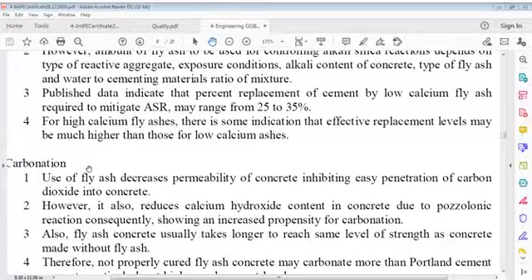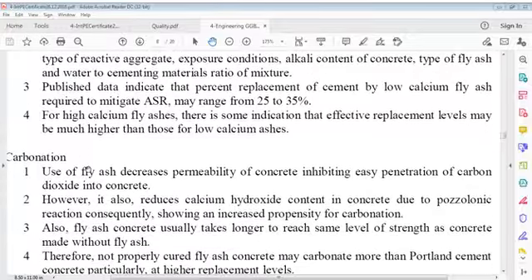Published data indicates that percent replacement of cement by low calcium fly ash required to mitigate alkali silica reaction may range from 25 to 35%. For high calcium fly ashes, there is some indication that effective replacement levels may be much higher than those for low calcium ashes. So low calcium fly ash requires 25 to 35% to mitigate ASR. This is low calcium.